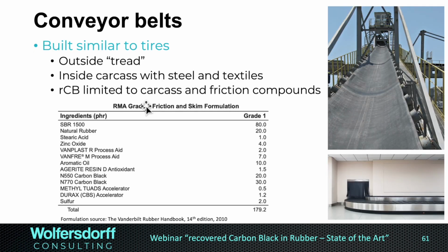Conveyor belts, for me, are pretty much similar to tires. We have the outside, which is like a tread, and we have the carcass with steel and textiles. RCB really is limited to the carcass and to specialties. This one recipe is a friction compound. If we want to have high friction on the outside, this is a friction compound featuring 550 and 770. I haven't seen that for a long time. I think nowadays that should be 774 and 772 carbon blacks. But both are in the realm of being able to be replaced with recovered carbon black. Airport conveyor belts use carbon black as well, could use recovered carbon black.